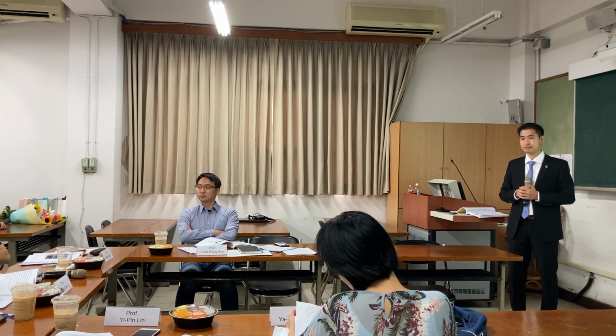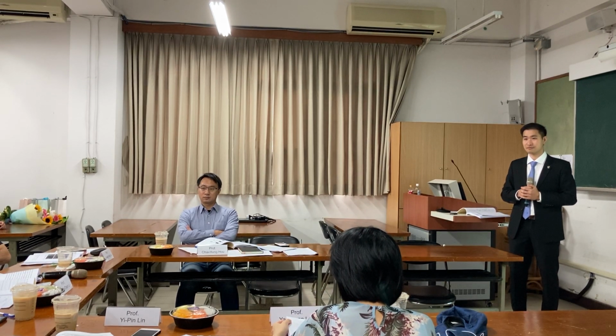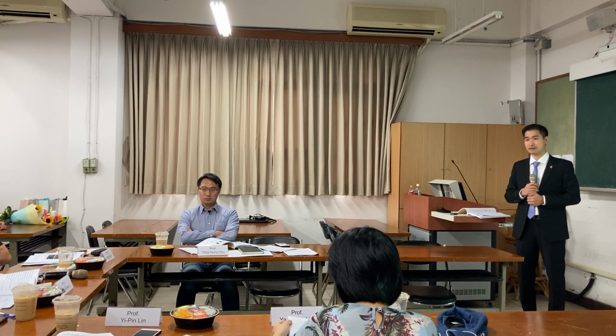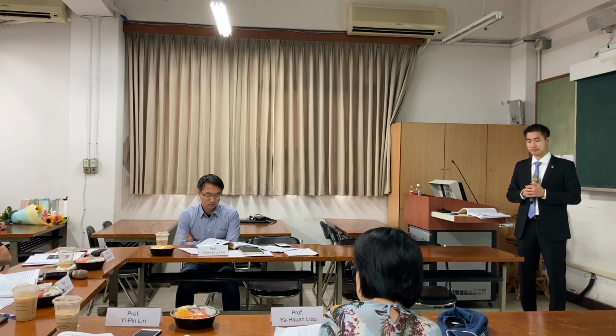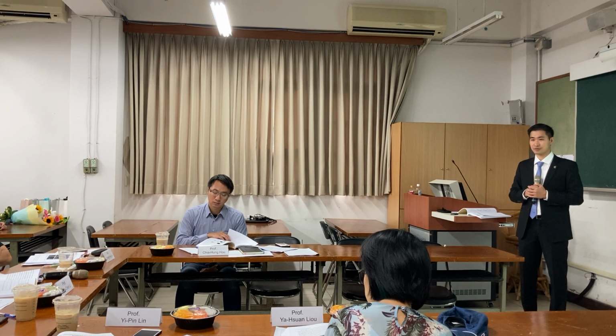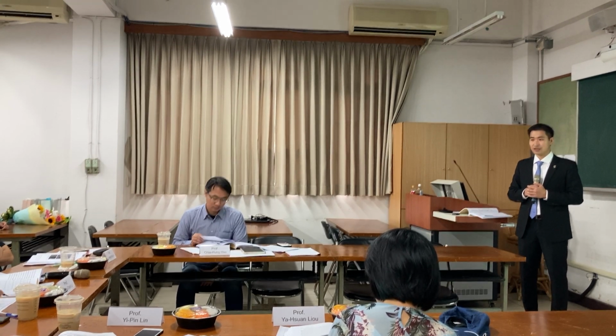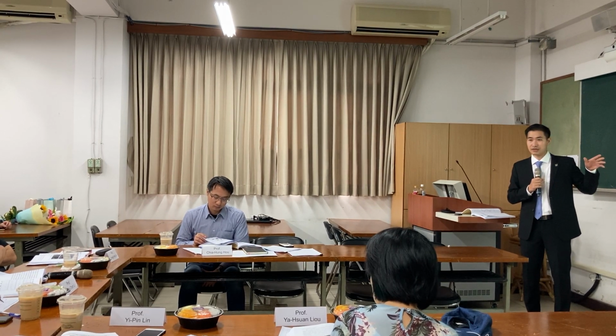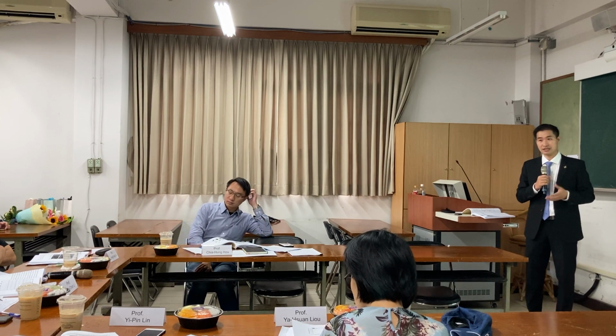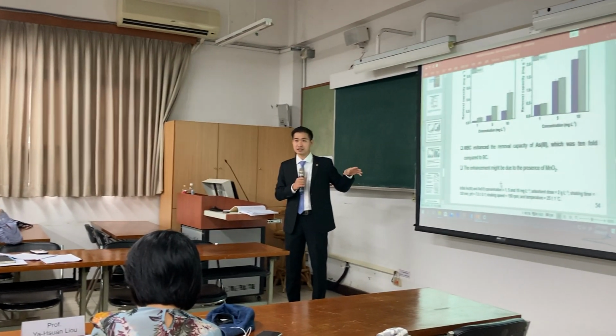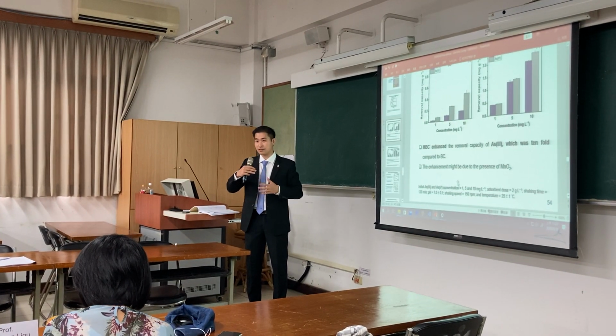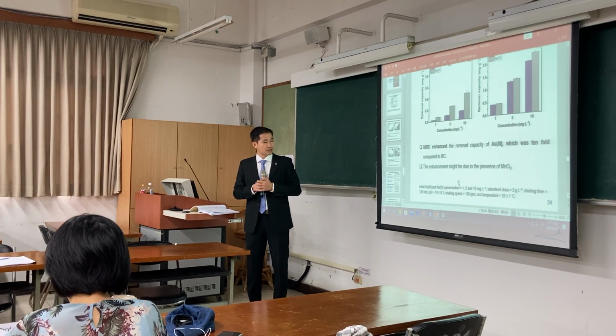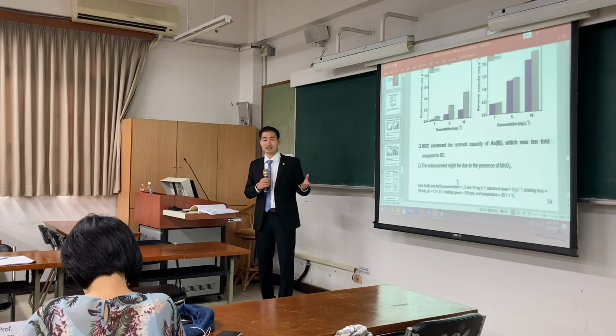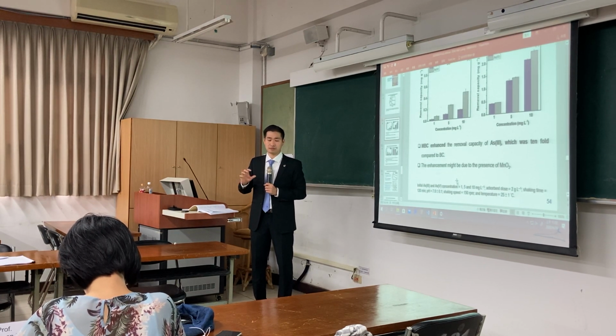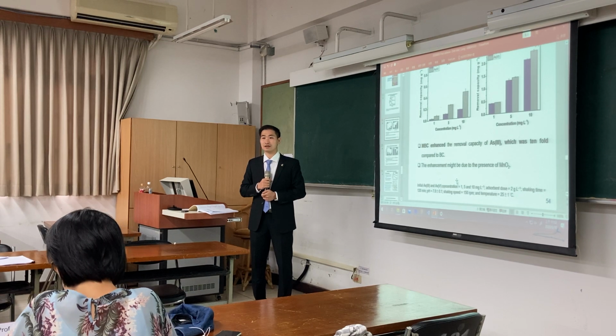But in terms of charge, I would expect a better performance for arsenic 3 instead of arsenic 5 because you have charge repulsion, negative versus negative, versus neutral. So why do you have a better performance for arsenic 5? If we just look at the electrostatic mechanism, it would be like that. But in this study, the mechanism for arsenic adsorption is not electrostatic attraction. Moreover, many previous studies mentioned that arsenic 3 has higher mobility than arsenic 5.